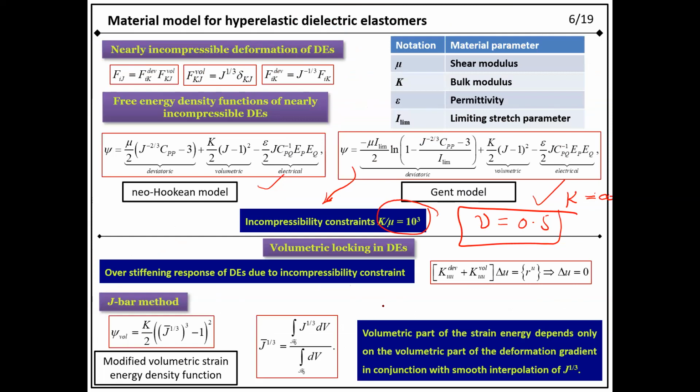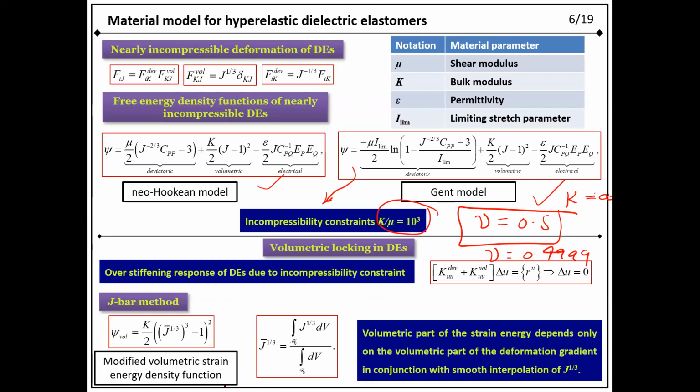What we generally do is assume that these materials are nearly incompressible. We take nu equal to 0.4999, something like that. In that case, this term will not become infinite. Although there will be a numerical instability, or the locking phenomenon, so we will not get what we require. So in order to remove such instability, the locking phenomenon, what can we do?